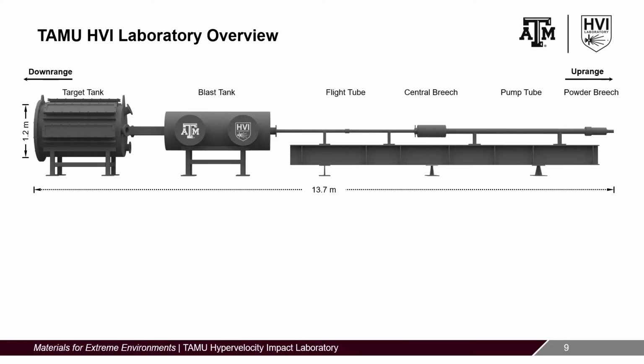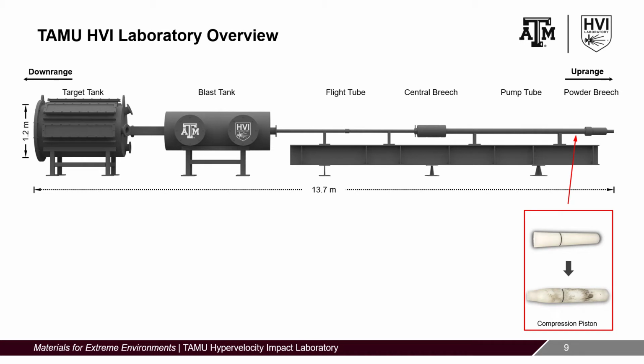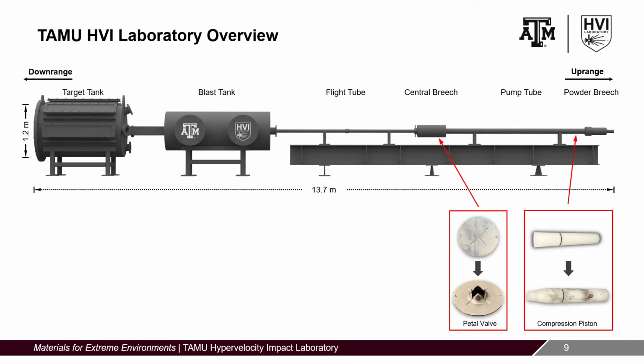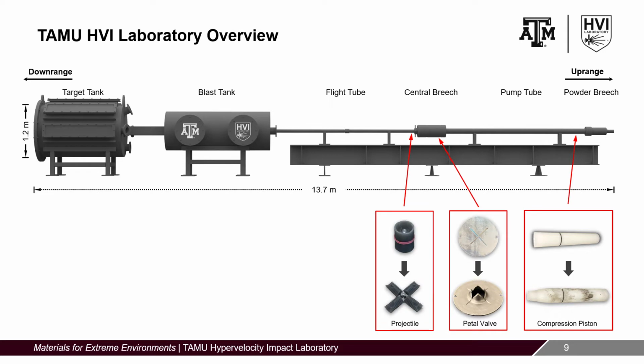Two-stage light gas guns accelerate projectiles by compressing a light gas, typically hydrogen or helium, to high pressures using a consumable polymer piston and a gunpowder charge. The gases released from the powder charge combustion propel the polymer piston down the pump tube, compressing the light gas. Once the light gas reaches a critical pressure, a diaphragm ruptures, releasing the high-pressure gas that accelerates the projectile. The projectile is protected during acceleration by a 4-piece polymer sabot. The sabot is aerodynamically separated from the projectile during free flight.